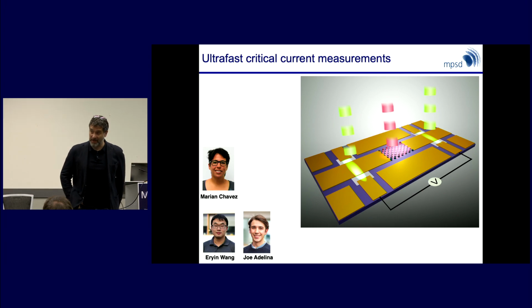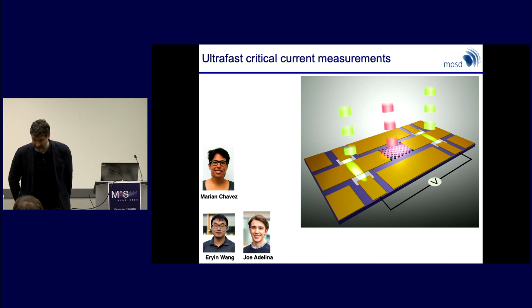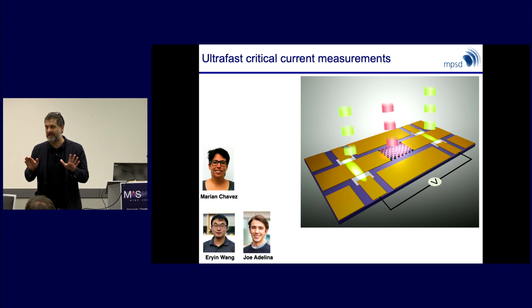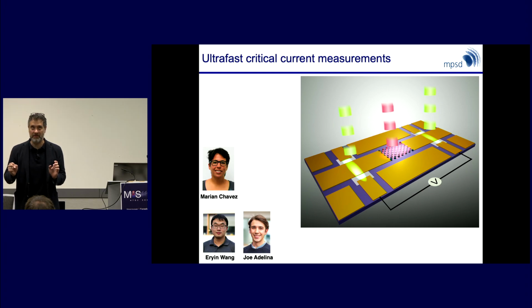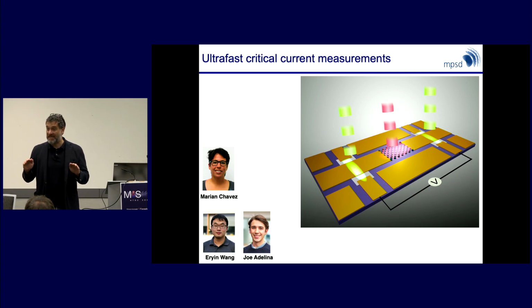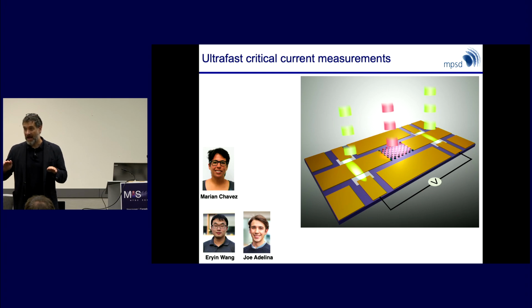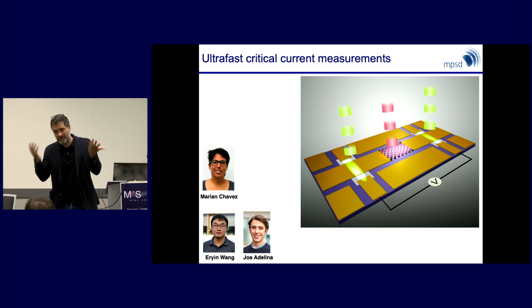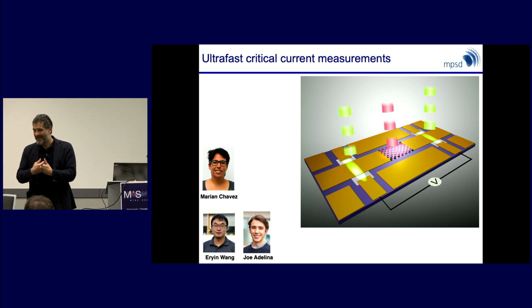So, it's possible that a serious transport person could do this. Generally, the problem is the following. If you have 4 probes, you need to keep the voltage constant at 2 probes, okay? If these pads are capacitively coupled to something and you change the conductivity in time, these guys are going to float like a balloon. So unless you do hard work to keep the capacitance small, it's very difficult to keep voltages constant. I mean, serious people do this, but we haven't figured that out yet. It's just hard enough that we haven't gotten to that point.